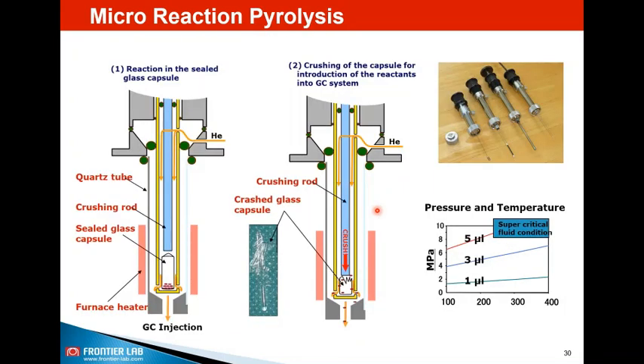Now let me go to the last part of my talk, which is basically the micro reaction pyrolysis. As I said in the beginning, not all samples can be done by a flash pyrolysis. In some cases, like the condensation polymer, you may have to use some kind of methylation or reactive pyrolysis step. And even for some types of condensation polymer, it is not sufficient to do the open reaction. You may have to use a closed reaction. Such reactions are possible with our system where we are using a glass capsule. In this glass capsule, you are taking your sample and the reagent, and you fuse the end, so that means it is closed. Then you attach it to the sampler.